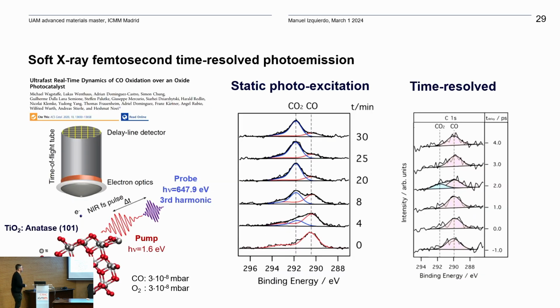Something that you can also do, and is very interesting, is study photocatalytic materials as a function of time. One of the test beds is the anatase phase of titania, because it's well known that this material has photocatalytic properties for many things.